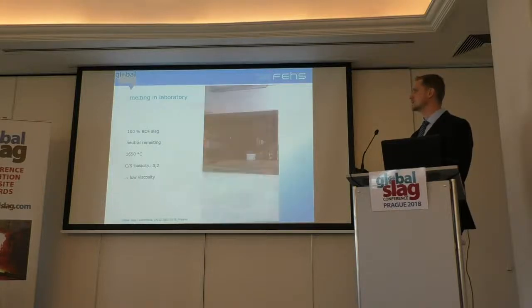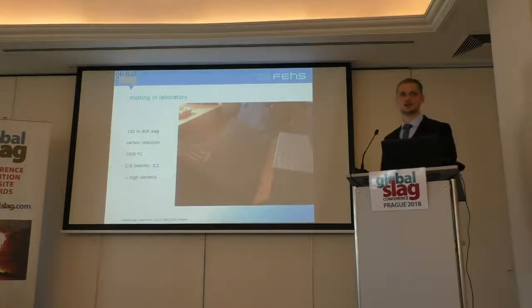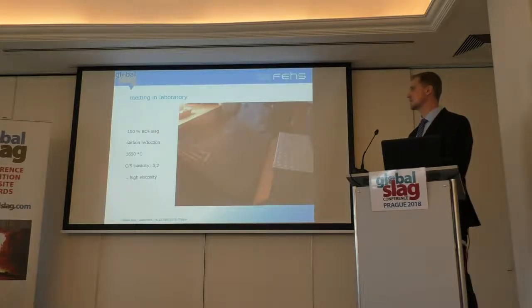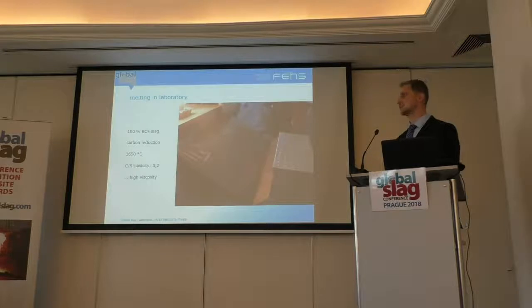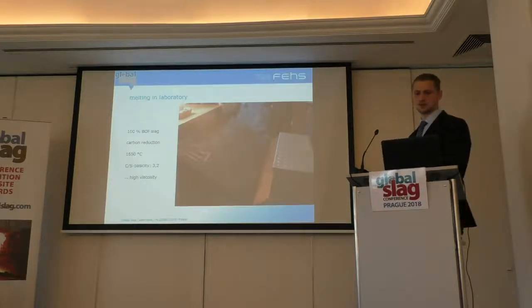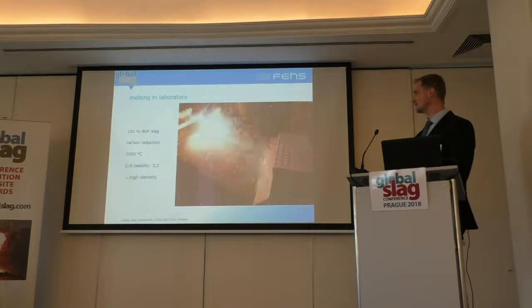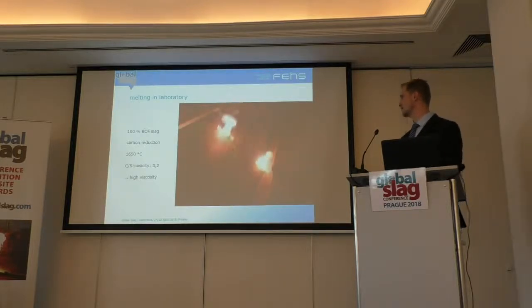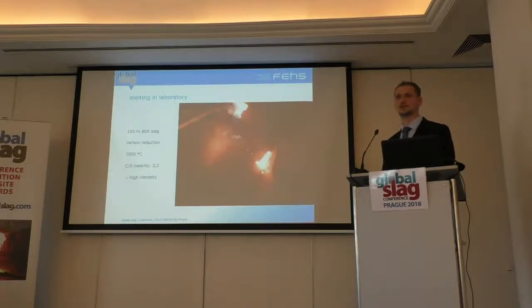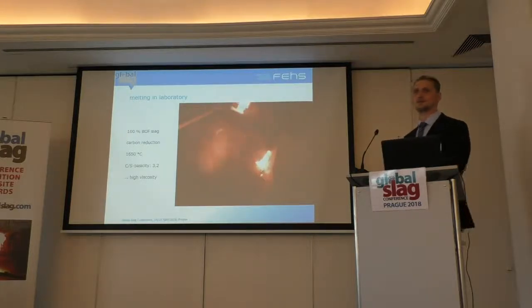So the first step in the project was to make a carbon reduction. We used the carbon crucible for this. The reduction was more or less 100% BOF slag, and we used 1650 degrees also, the same basicity. There we got some problems. As you can see here, there is nothing liquid in it. We had a lot of problems to get this material out of the crucible, and when you imagine this happens in a steelwork in a big scale at 25 tons, a lot of work, and you don't want to have this.